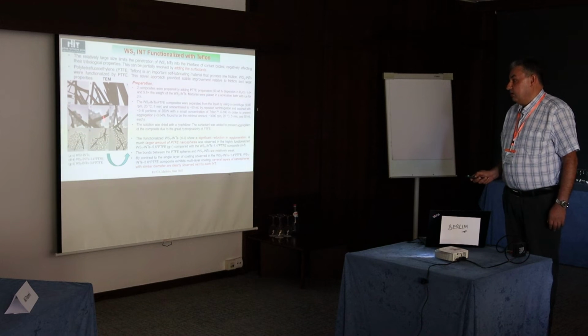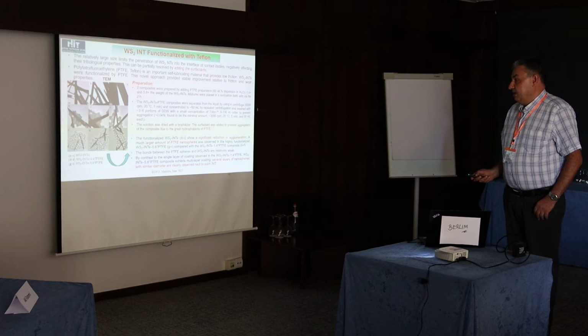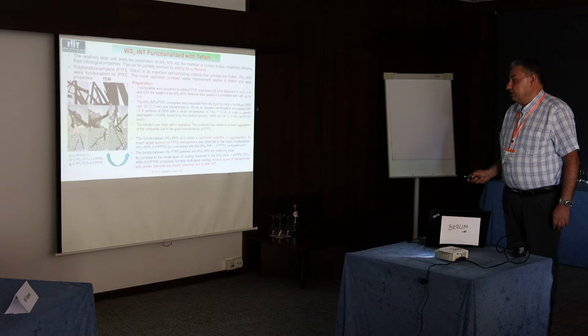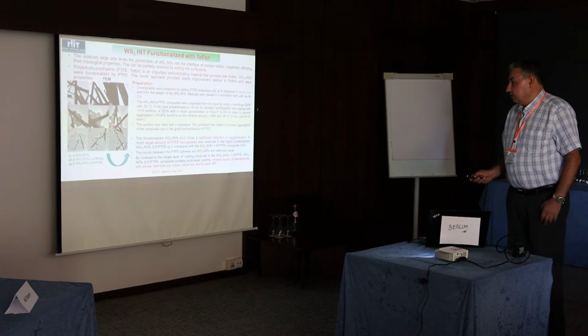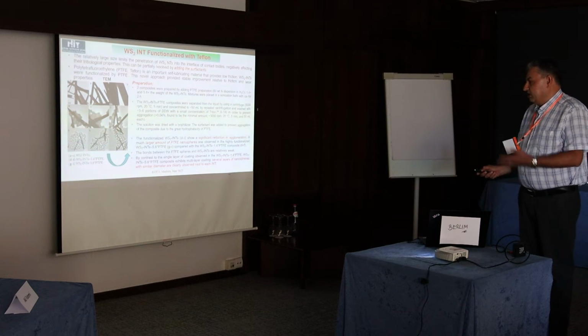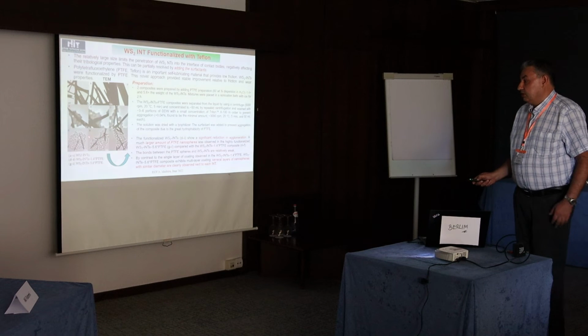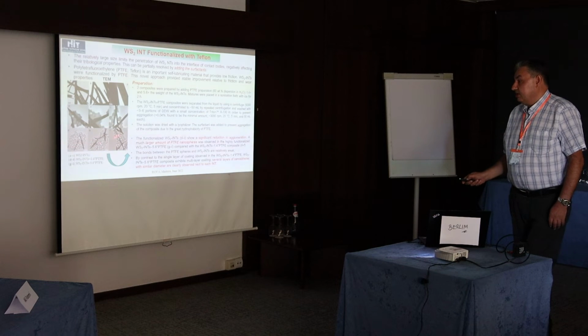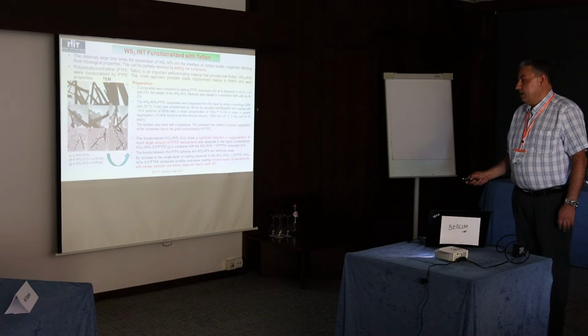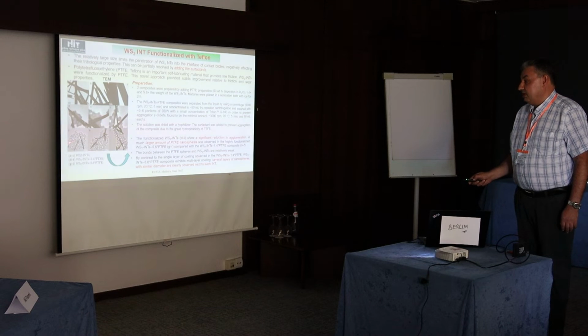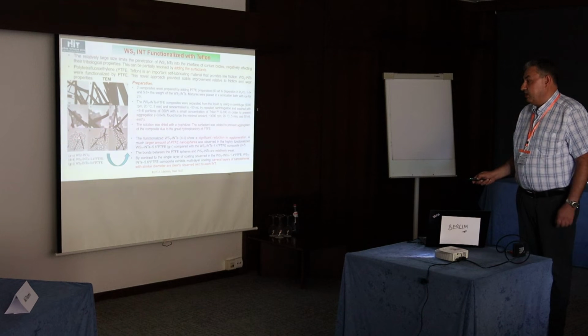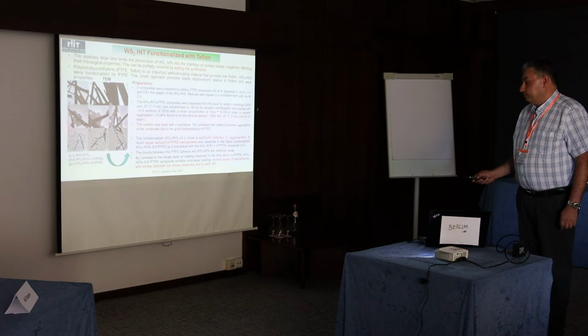How can we see that they are covered with Teflon? By TEM images. You can see a reduction in agglomeration of nanotubes. I will show the quantitative analysis of the average size in the next slide. But as we increase the concentration of Teflon, you can see that the tubes are more and more separated, and these giant nanospheres are mainly related to Teflon.